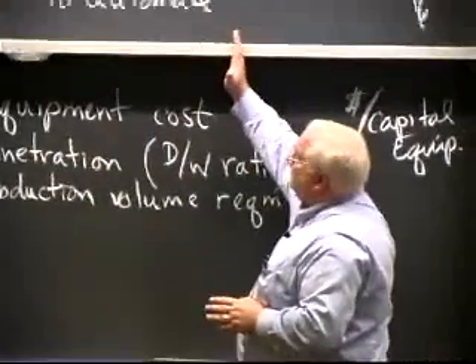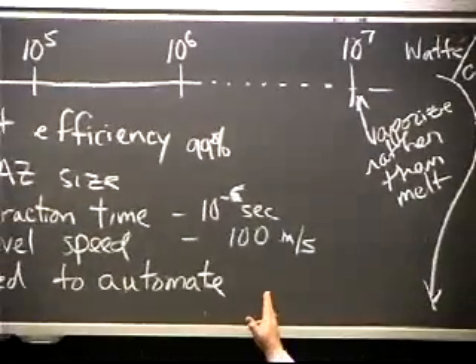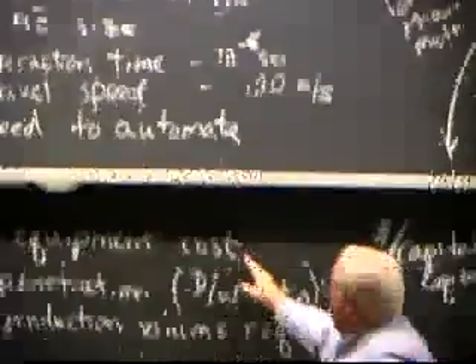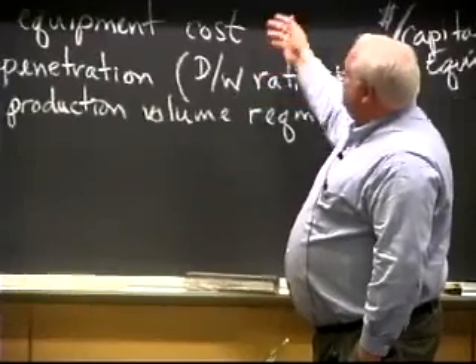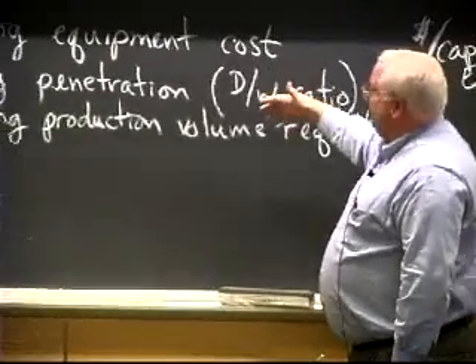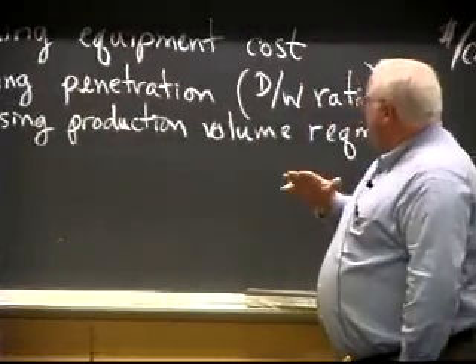They also have blanks that are not just rectangles. When you stamp out sheet metal from the steel mill, it comes in a big roll, and it's going to be rectangular or square. You can have square if you want. That's just a subset of rectangle, right? Now they actually can make these, two different rectangles sticking together, and so they actually save on scrap cost. So that's been one of the big things in the last 10 years is tailor welded blanks, because of the very high productivity or high speed of welding of lasers. And they don't use as much electron beam certainly for automotive assembly, because electron beam has to go in a vacuum, and we can talk about that later.